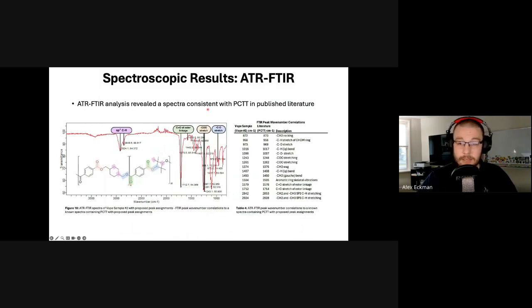The next thing that we did is we took a FTIR spectra of it. And what FTIR does essentially is it shows us functional groups. And this was helping us now get a better picture of what the molecular structure may look like. And we found a handful of pretty key stretches here. And then when comparing it to a known spectra of PCTT in literature, we find almost identical overlap. But this was the first kind of indication that we could have a polyester, mainly based off of the carbonyl and carbon oxygen stretches that we observed.